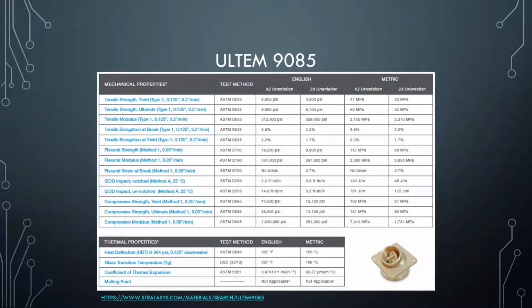Here are some mechanical properties. Of note, tensile strength at yield and ultimate of the resin material report at 47 and 69 MPa respectively. Heat deflection temperature is 153 degrees C and glass transition temperature is 186 degrees. PEI is amorphous and therefore has no melting temperature. Ultem 9085 is readily available for purchase, and current as of this writing could be found for $125 for half a kilogram of 1.75 millimeter filament for FDM.